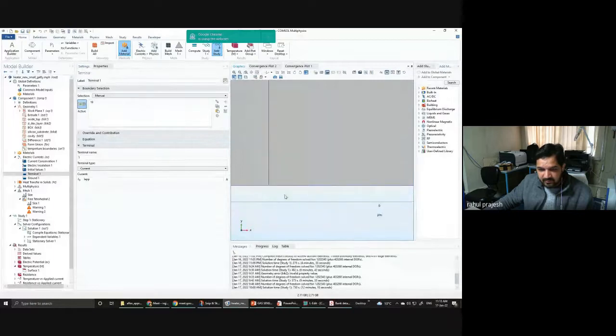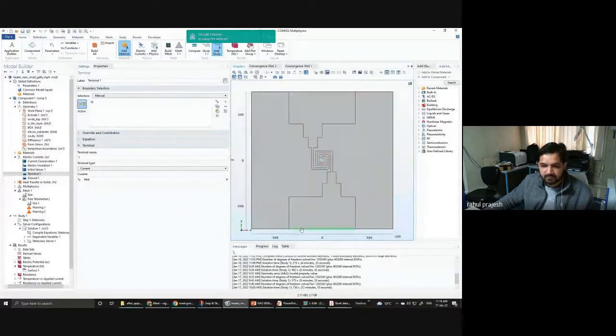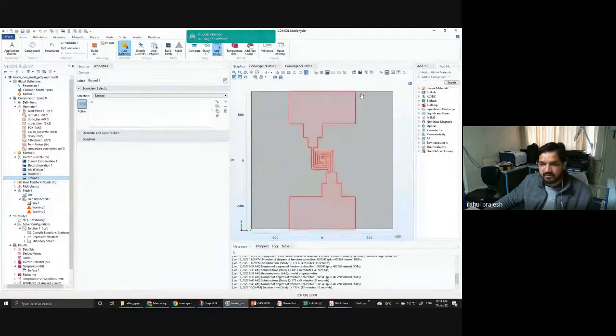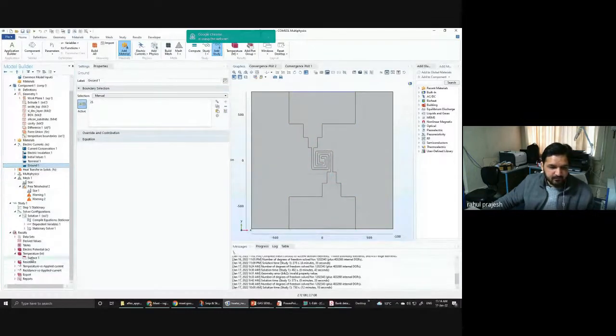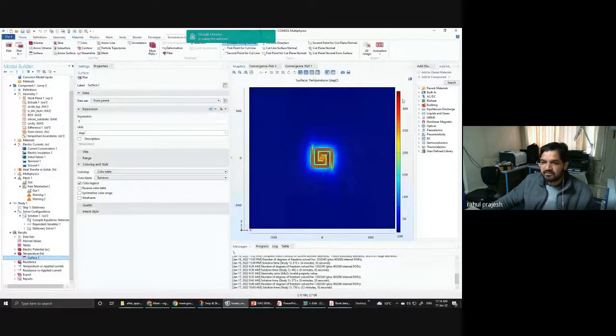This electrode is blue, okay, and this is black. So this blue is selected. That means on this electrode I have applied the current, and the other electrode is ground. So this is my ground. So from here to here, the current is flowing inside this coil. So when you flow different values of current, you can see that there is an increase in temperature. As you see, the temperature is good enough, 300, 350 degrees centigrade for gas sensing application.